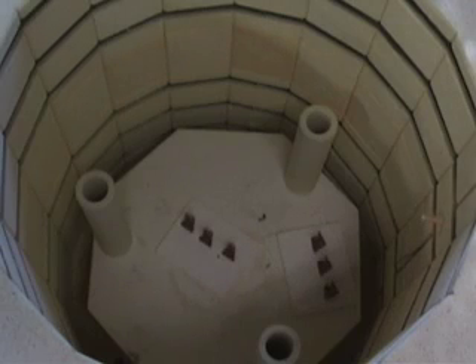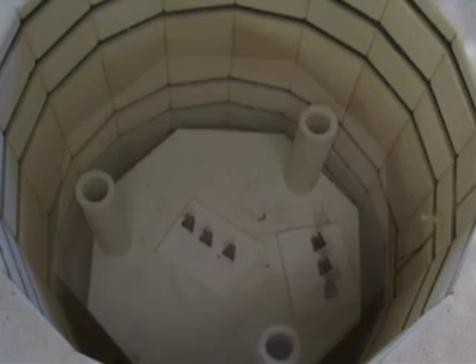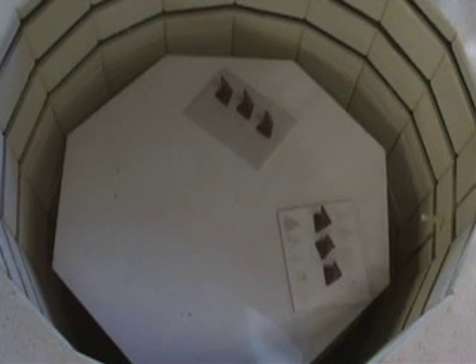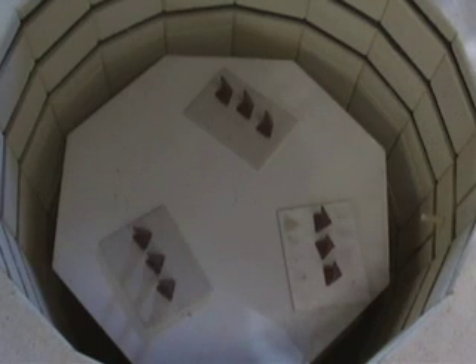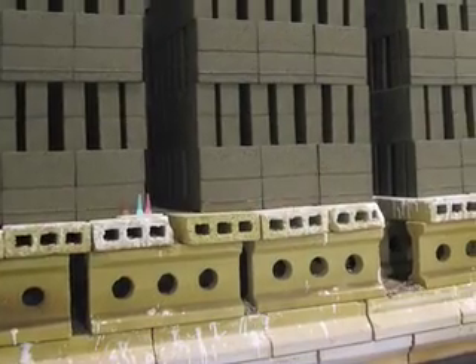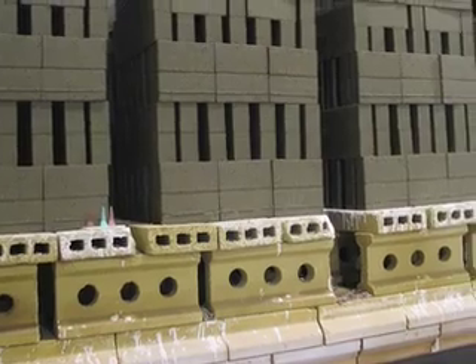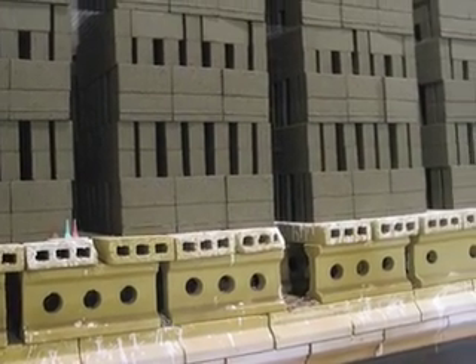Cone placement in a kiln is basically determined by the size of the kiln and perhaps what it is that you're trying to find out within the firing of the kiln itself. For normal firings, several locations are typically used. For small kilns, those of 2, 5, 10 cubic feet, cones would be used at the top and perhaps the middle or the bottom, several cones within a firing. In larger kilns, typically used within, let's say, the structural clay industry, thousands upon thousands of bricks are being fired on a kiln car.